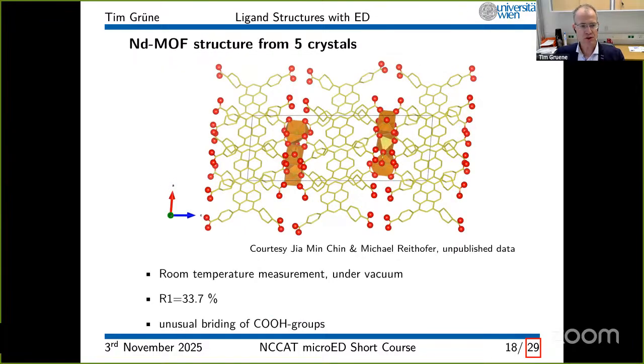This is the very structure, just for completeness. You see MOFs have these metal centers, and they're coordinated by these organic compounds. This was a room temperature measurement. You don't always need to cool down to liquid nitrogen, which makes life a lot easier in terms of handling the sample holder. The R-value of the structure is super high. Even for protein structures, it would be very hard to publish this structure. But when you do electron diffraction, you start getting used to these bad statistics. And it's more important to look at the structure itself and what it tells you than to rely on the statistics that you get. In this structure, the bridging of this neodymium MOF was quite unusual.